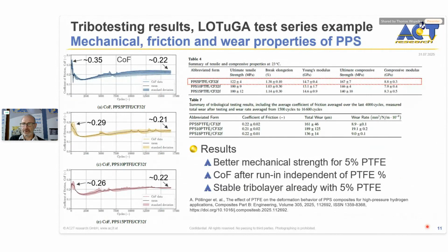So the first results we got under nitrogen atmosphere are, you can see on the left side, the coefficient of friction curves throughout the tests. It was run up to 16,000 or 17,000 cycles. And the upper left graph is showing the results for the PPS with 5%, then 10%, and then 15% of PTFE.